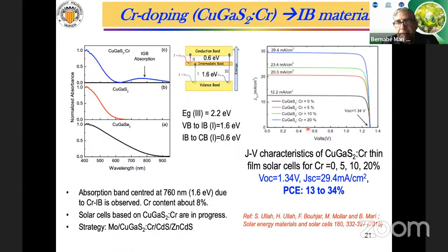On the right, this slide shows the current density as a function of the potential, the JV curve, for different materials, copper gallium sulfide with different amounts of chromium. As you see, as the chromium doping increases, the open voltage is the same, but the short circuit current increases a lot.